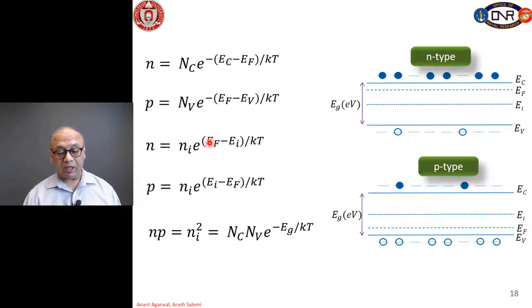Similarly, p is described as Nv, which is the effective density of states in the valence band, times the exponent of negative of Ef minus Ev over kT. So again, if we make the p-type material more p-type by doping it with more acceptor atoms, then the Fermi level moves closer to the valence band edge. In other words, Ef minus Ev decreases.